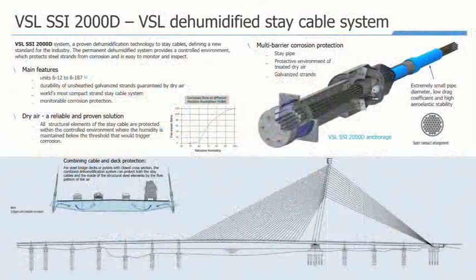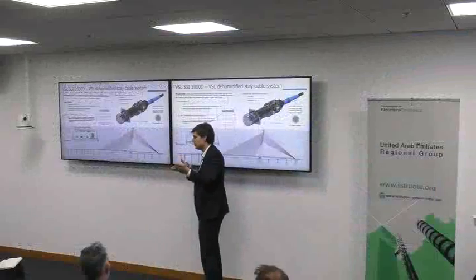If you see that graphic here, these are basically the corrosion rates according to humidity. And what you find is that with a relative humidity of 60% and below, you have almost no corrosion. It picks up very fast afterwards, but below 60%, no corrosion happens. And all dehumidification plants usually work at 40%. So the idea is to have a closed loop of dehumidification. This is the principle applied to this Hong Kong project, for example. You keep retreating this air, and your machine is just there to compensate for leakage. As soon as you have leakage, you have to refeed with dry air. So you dry only the air you add on top in this circuit.